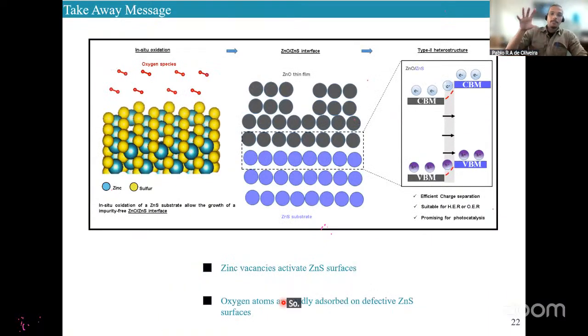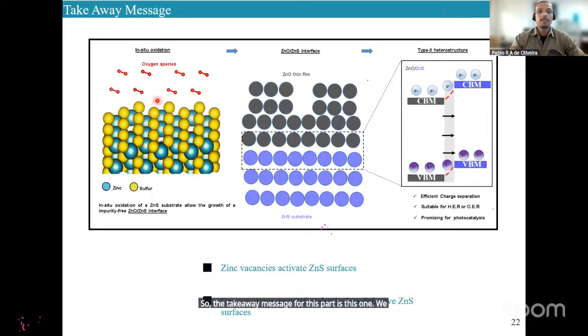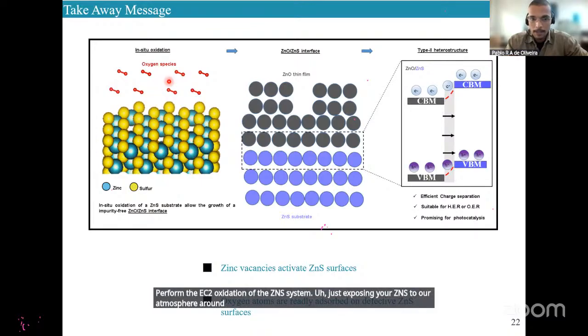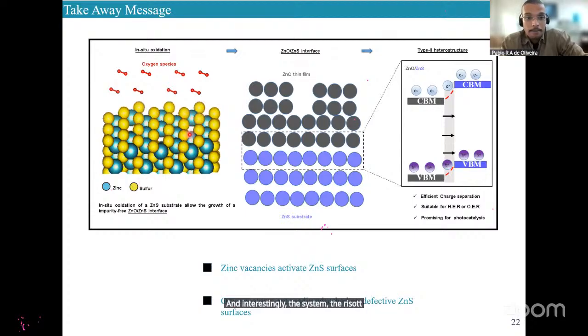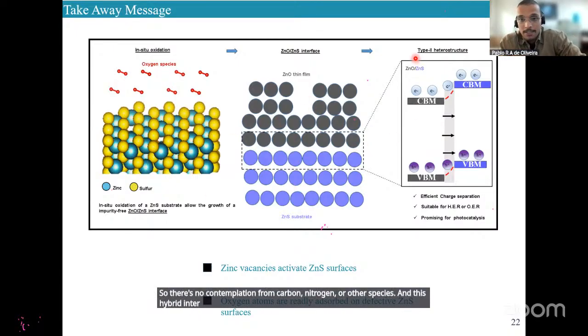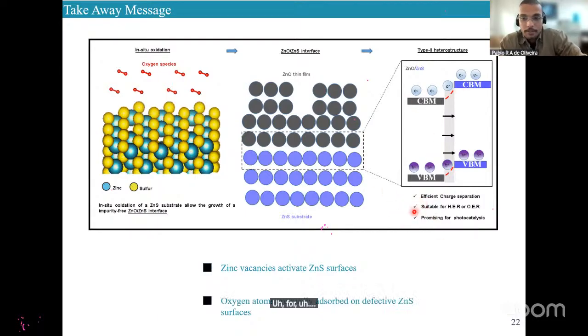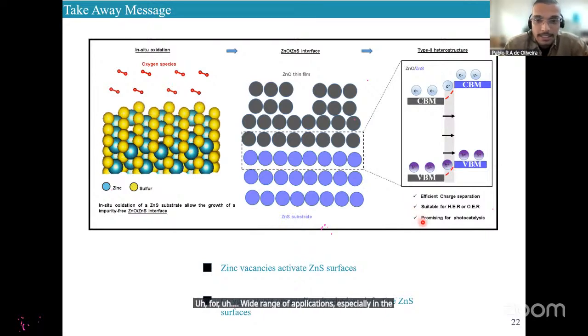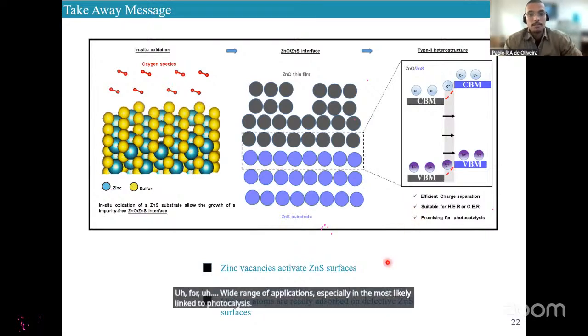So the takeaway message for this part is this one. We can just perform the in situ oxidation of the ZnS system, exposing your ZnS to an oxygen atmosphere of around 10^-5 millibar. And interestingly, the resultant system is impurity free, so there's no contamination from carbon, nitrogen, or other species. And this hybrid interface displays suitable levels for a wide range of applications, especially those linked to photocatalysis.